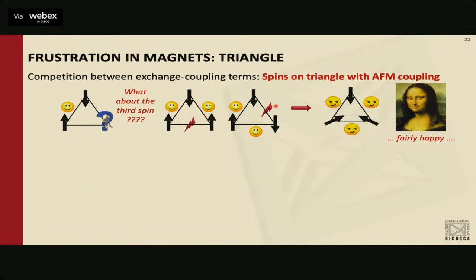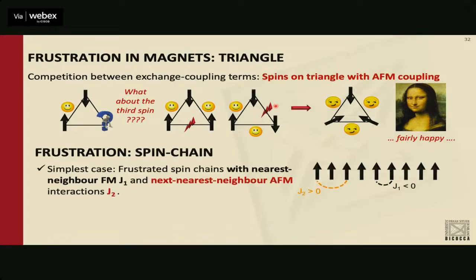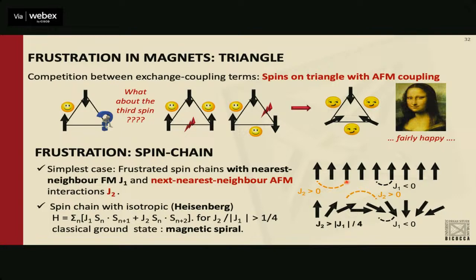So if your lattice is such that it allows exchange frustration, then it has the necessary ingredient for non-collinearity or non-coplanarity to develop. Even if you have a simple spin chain with a small first nearest neighbor coupling and a large, anti-ferromagnetic second nearest neighbor coupling, then the ground state is a spiral.